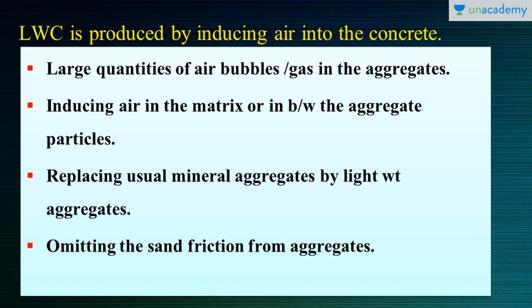The first method is to induce air bubbles or gas in the aggregates themselves — that means making the aggregates more porous, or replacing them with more porous aggregates. The second way is inducing air in the matrix or between the aggregate particles — that means introducing air in the concrete matrix itself, or creating a small amount of voids between the aggregate particles.